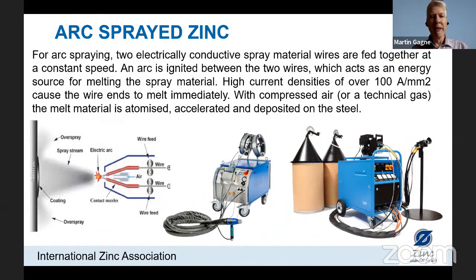Now for arc spraying, we use two electrically conductive wires. When these touch, they create an arc, and then that melts the wires. And again, with compressed air or other gas, we can propel those liquid droplets onto the steel. So some equipment we can see on the right-hand side, a more heavy-duty installation. The wire is coming out of a barrel. In the middle, this is a more portable application. A smaller reel of the zinc wire is attached to the top of the power supply, which is very similar to a welding power supply.